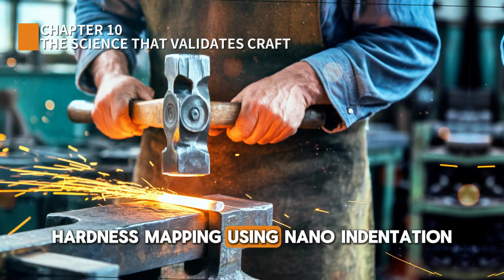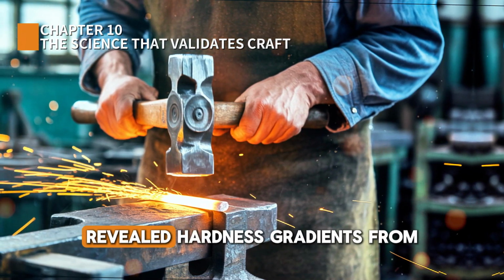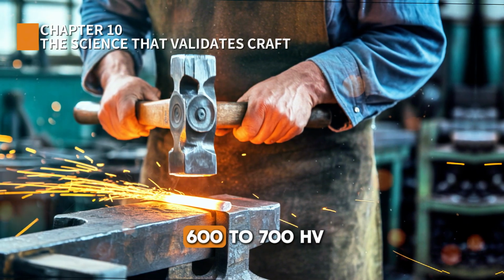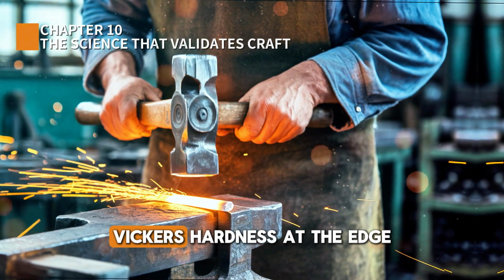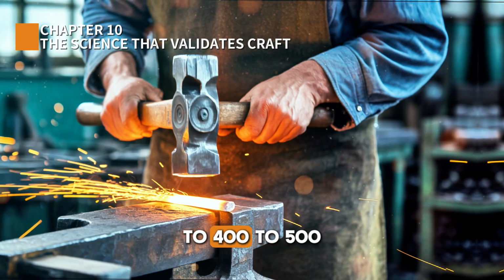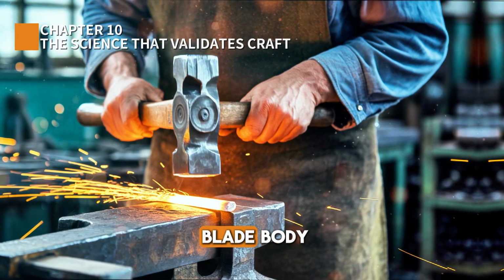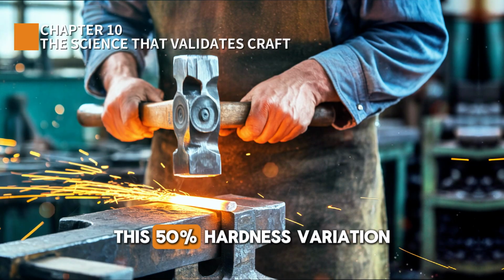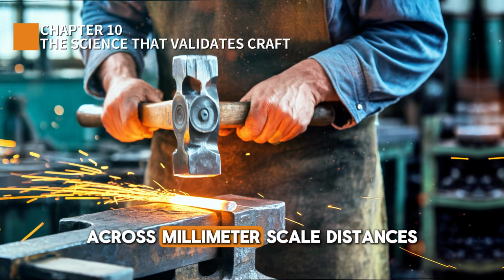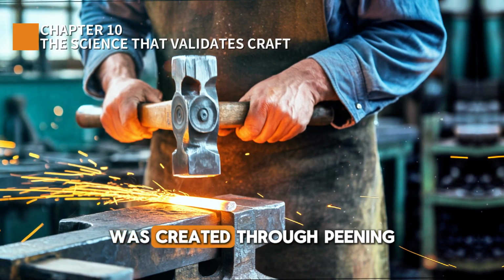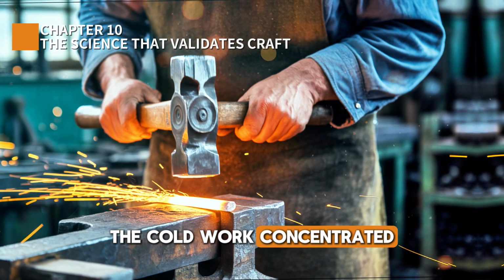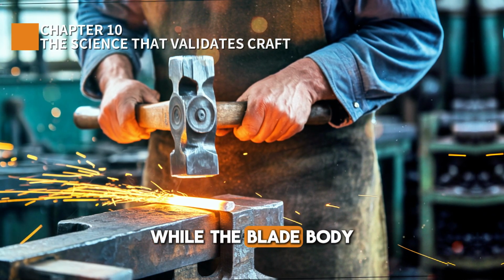Hardness mapping using nano-indentation revealed hardness gradients from 600 to 700 HV, Vickers hardness, at the edge to 400 to 500 HV in the blade body. This 50% hardness variation across millimeter-scale distances was created through peening. The cold work concentrated at the edge, while the blade body remained softer and tougher.